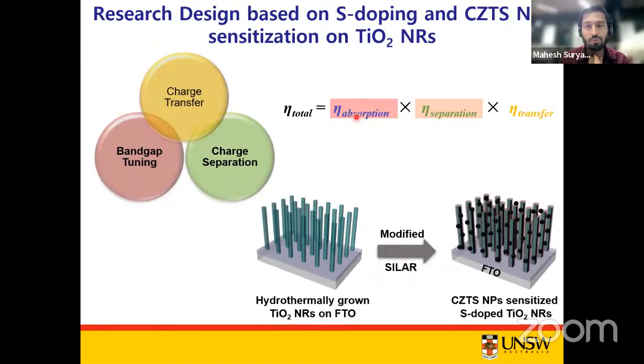Usually the light absorption can be improved by simply doping sulfur into TiO2 lattices. When we dope sulfur, usually the band gap is reduced. I will explain why there is a reduction in the band gap after doping sulfur into the TiO2 lattices. We can also improve the absorption of TiO2 by sensitizing it with visible light absorbing CZTS nanocrystals, which have a band gap of about 1.5 electron volt. So that is how we can improve the absorption of these TiO2 nanorods.